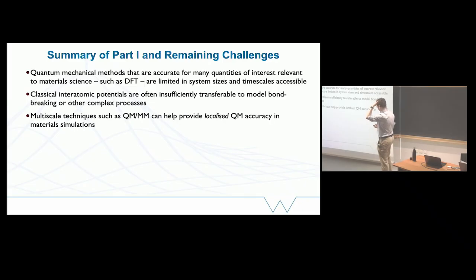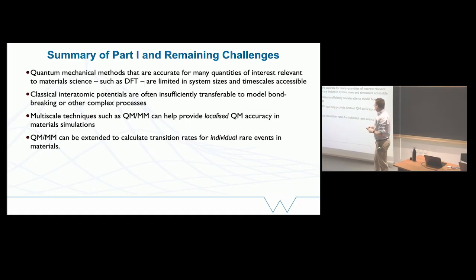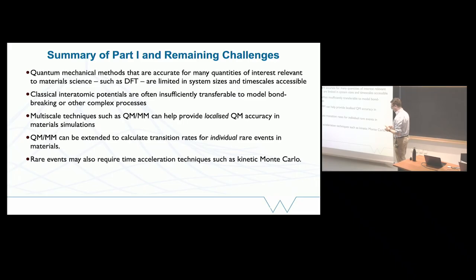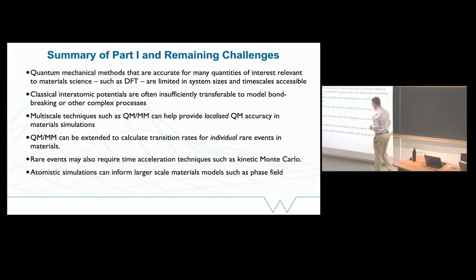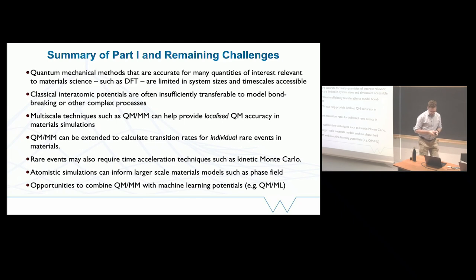Multiscale techniques such as QM/MM still have some value, I think. We'll talk about how they fit into the modern machine learning world in the second part, where you need localized high precision. So you know that your model is good enough in most of the system, but there are a few spots where you might need higher accuracy. And they can be extended to calculate transition rates if you know what your individual rare events are that you'd like to calculate. Then you can feed into kinetic Monte Carlo, and you can inform larger scale materials models. So I showed a continuum model. That could be a phase field model just as well. Is that the last point? No, okay. And there are clear opportunities to connect things I've been talking about in this first half with machine learning, which is what we'll do in the second half.